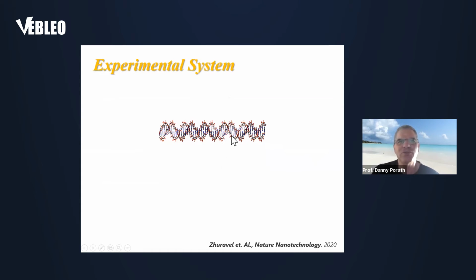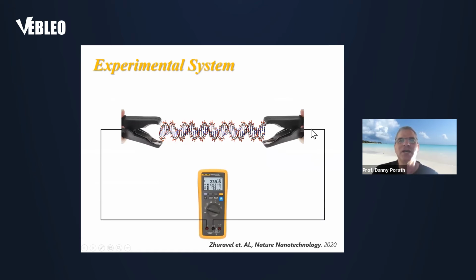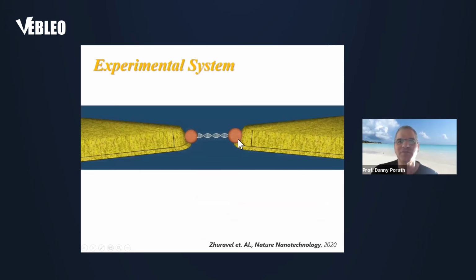So how did we do that? You have the molecule, and then we want to trap it between electrodes, apply voltage, and measure current. Easier said than done at the nanometer. So the experimental system that we chose is two metal electrodes that are fabricated by e-beam lithography, where in between we have an object that we call a dimer.